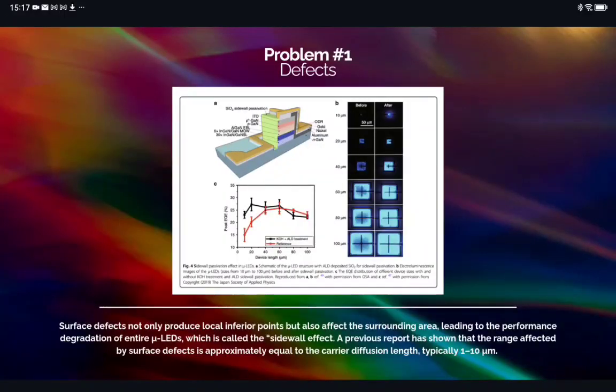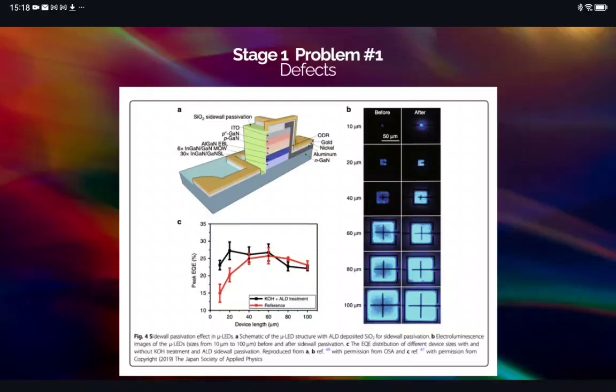Surface imperfections also impact the surrounding region, ultimately causing the performance of the complete micro-LED to deteriorate. This is called the sidewall effect. According to an earlier study, surface imperfections generally impact an area between 1 to 10 micrometer, which is roughly comparable to the carrier diffusion length. Therefore, surface treatment is necessary to minimize the sidewall effect.